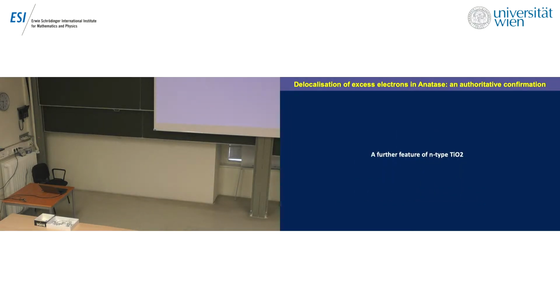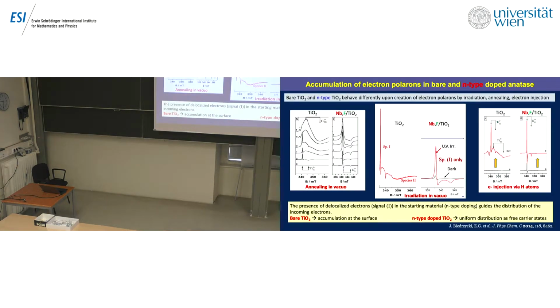Okay, I have just 4 minutes, but there is a final feature that I want to show because it's really interesting, and we were not able to tell the community this message probably in a clear enough way. Let's go back again for a minute to the n-type TiO2, so enriched with fluorine or niobium, it is the same system. There is something that makes a strong difference between pristine anatase and this doped system. If you have initial doping in the system, any evolution of the system is conditioned by this doping.